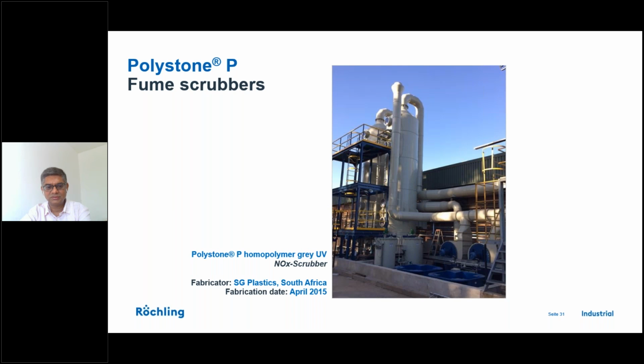Fume scrubbers. Here, as you can see, we generally recommend you to go for material which is UV stabilized. We have in our range Polystone P homopolymer as well as copolymer sheets which are UV stabilized. So when you are having any outside exposure, whether it is ductings or blowers or chimneys or scrubbers, better to go with the UV sheets, so that there is no detrimental effect to the material when it is exposed to direct sunlight.